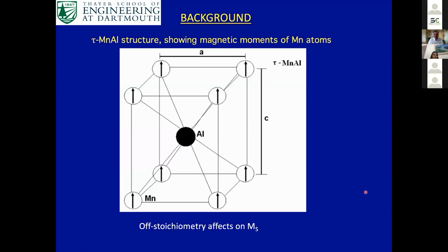So this is the crystal structure for manganese aluminum. It's a tetragonal crystal structure where you have an aluminum atom in the center of the unit cell. Now, if you put manganese atoms next to each other, manganese has a large magnetic moment, but the magnetic moments line up anti-parallel when manganese atoms are adjacent. But in a crystal structure like this, if you put an aluminum atom between those manganese atoms, the magnetic moments line up in the same direction.